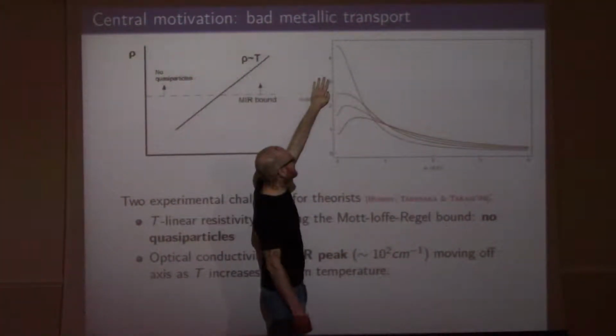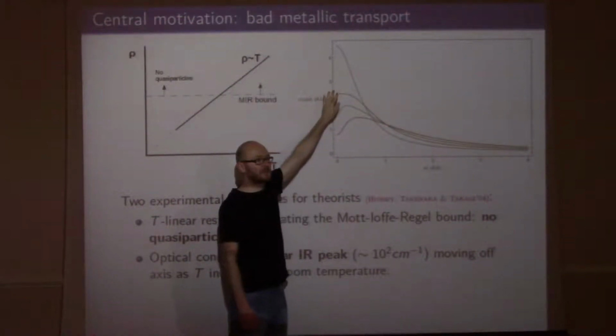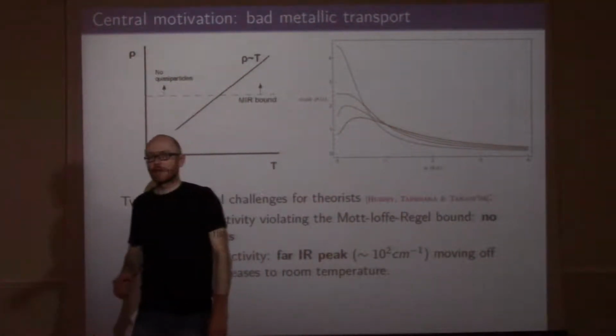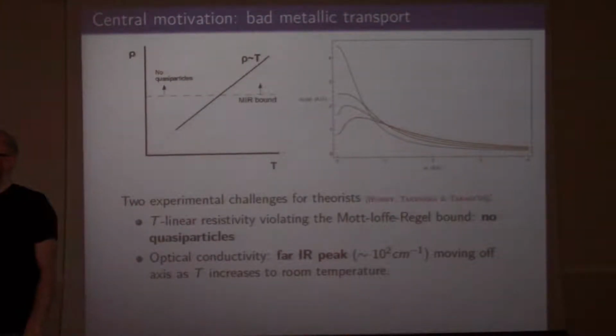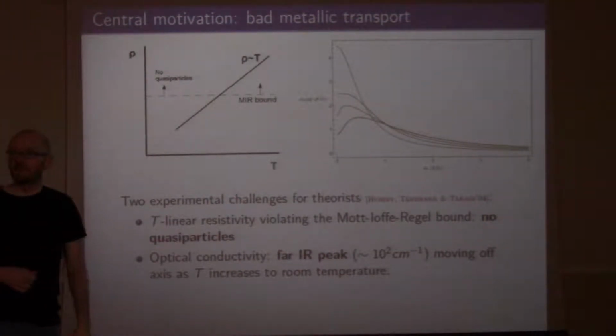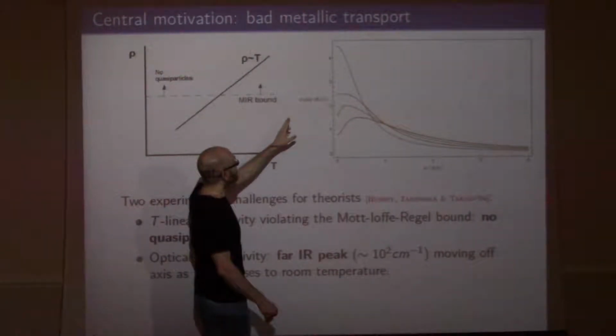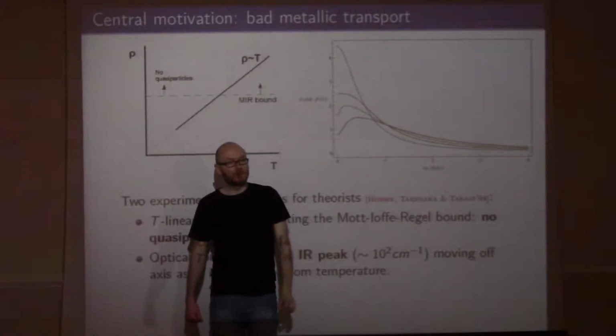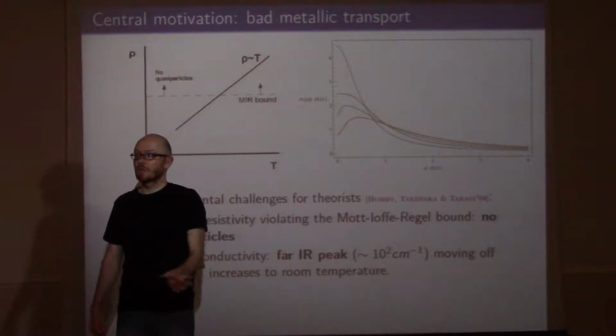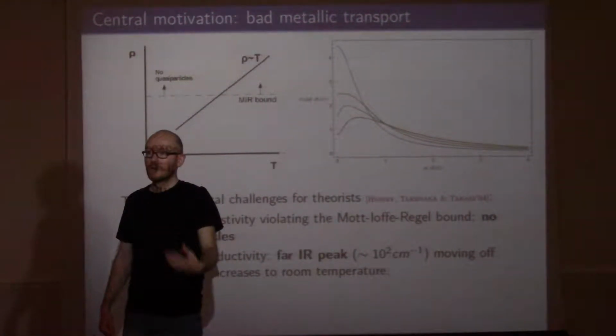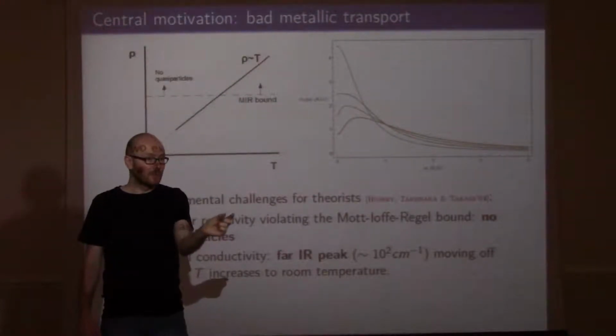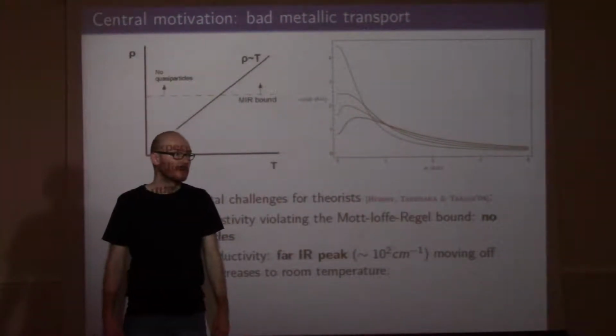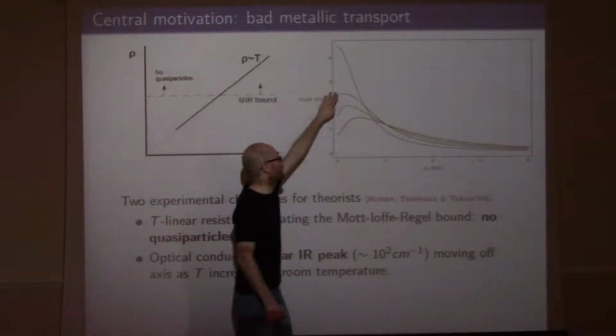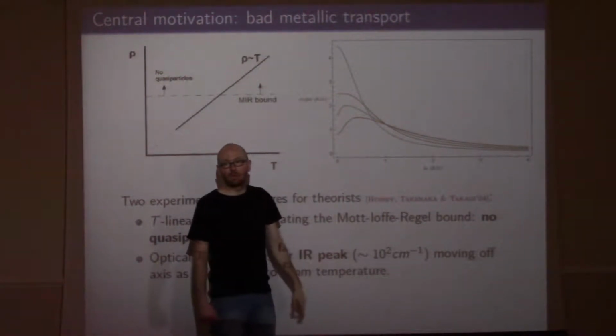At relatively low temperatures, you have these peaks at zero frequency. So this is very much like what we saw in the case of a metal where momentum relaxes slowly. You remember that we had this sharp Drude peak that was centered at omega equals 0. So this looks like that, except that here the width of the peak is of order the temperature. You remember I was telling you that in order for this slow momentum relaxation picture to apply, you needed the width of the peak to be orders of magnitude smaller than temperature, and here this is already not the case, even though this is a peak centered at omega equals 0.